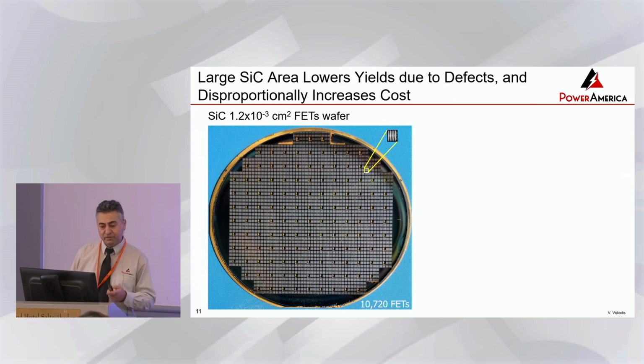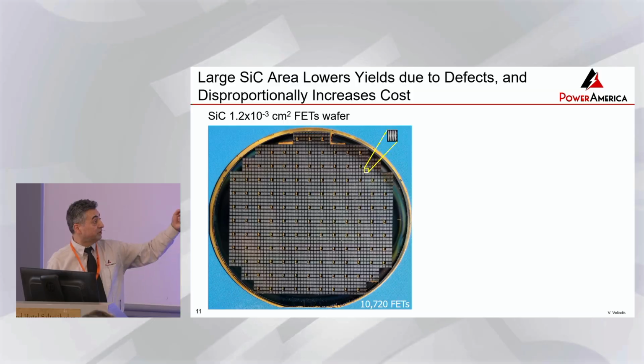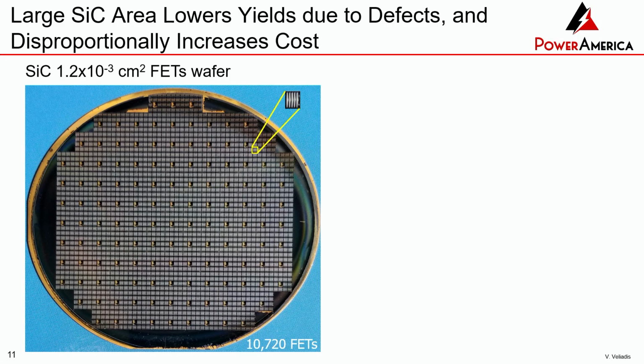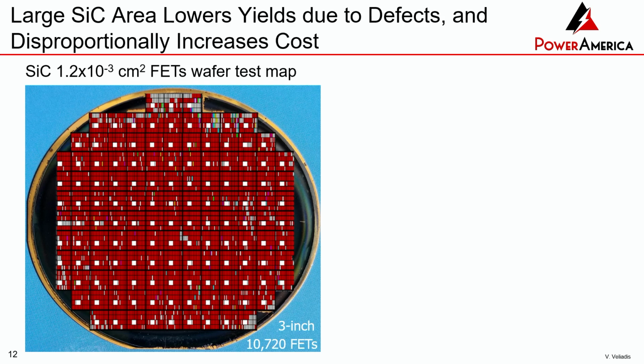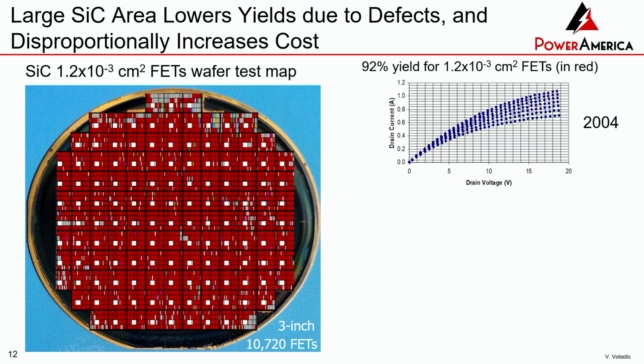And just to give you an idea, this is devices that I was building in the early 2000s, 1.2 10 to the minus 3, very small device, right? You can see there's more than 10,000 of those devices on the wafer. And this is the wafer map, the testing. Everything that you see in red is a good device. And for those small devices, I was getting a yield of over 90%, which was really good.